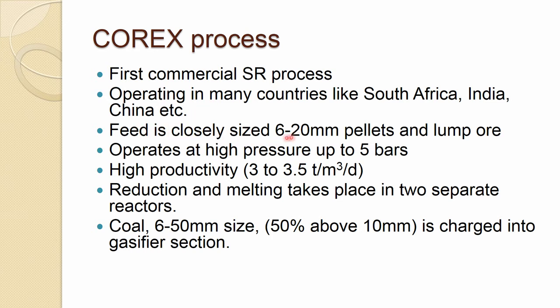Feed is closely sized 6 to 20 millimeter pellets and lump ore. So, remember in this one you have to feed as pellets or lump ore. So, it does not take fines, this is the difference in this one. Operates at high pressure up to 5 bar, it has quite high productivity.